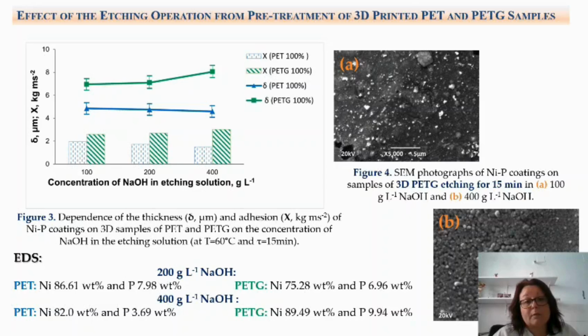From the obtained experimental data on the influence of the concentration of sodium hydroxide in the etching solution, it was found that when metallizing 3D PET samples, it is recommended to work with 100 gram per liter sodium hydroxide, whereas for metallization of 3D PETG samples, a more concentrated solution containing 400 gram per liter sodium hydroxide is needed.